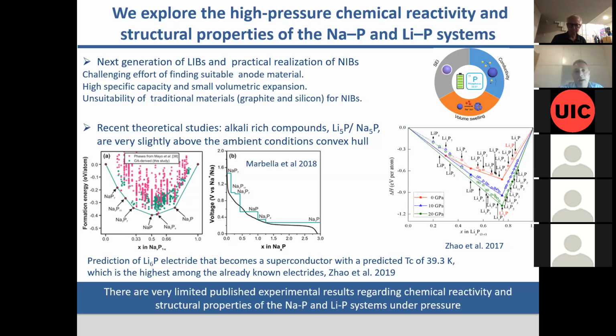And as I mentioned, we managed to retrieve the material after removing it from the diamond anvil cell and measure the EDX, so measure the composition. I agree that EDX is not perfect for this kind of elements, but at least it was clear that we are looking at something one-to-one, and also that it's uniform. So I think we have more than enough evidence to claim that this material was synthesized. But I agree, and I tried to highlight this at the beginning, that this field is very difficult because you don't know a priori what you have synthesized. And we all know that the probing techniques available in situ are very limited. So we need to acknowledge theory for giving us some tool to at least compare and have some support there. I don't know if you are happy with my response. I'm very happy. Thank you.